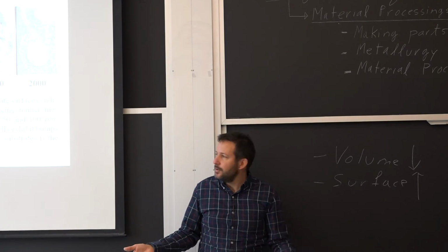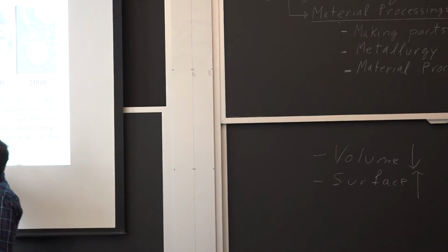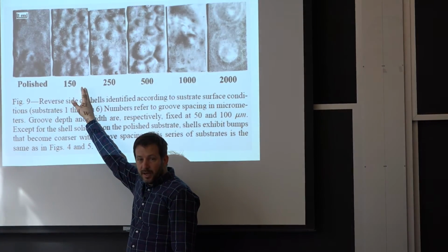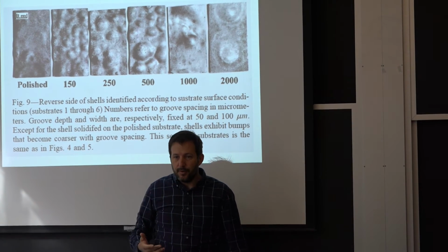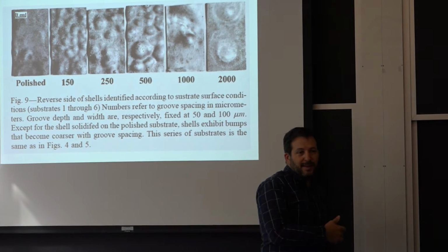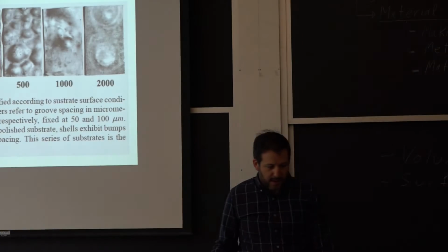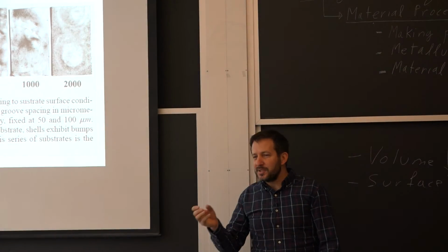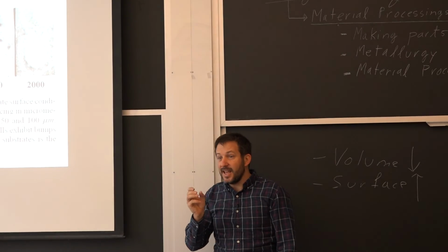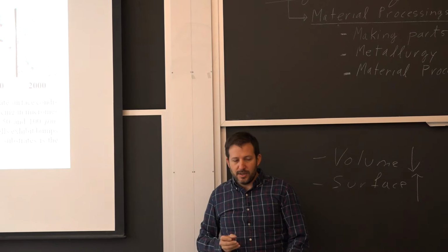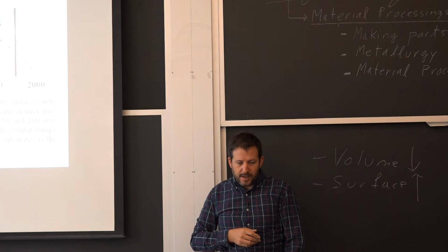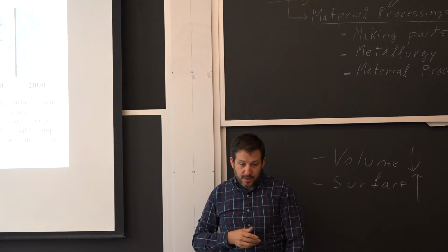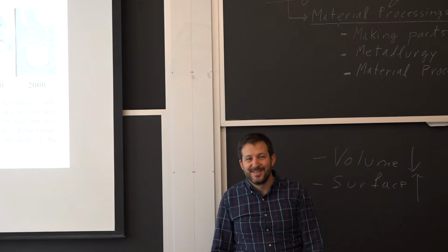So what you have to do is use a very coarse grit of sandpaper to prepare the surface so you get plenty of nucleation sites. And yeah, it had a bunch of bumps, but they're all about the same and they're not that thick. So it's almost homogeneous. And yeah, that's the story.